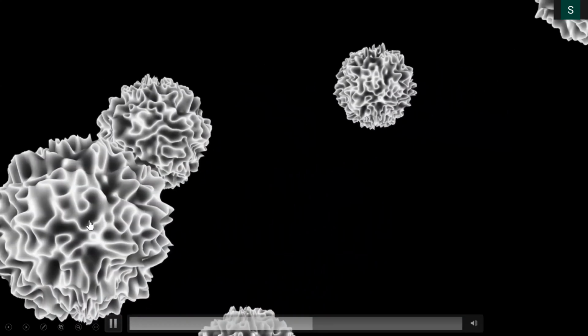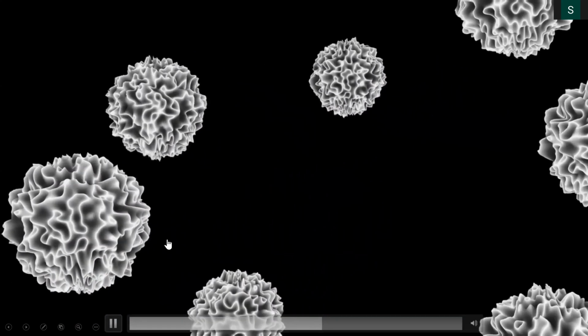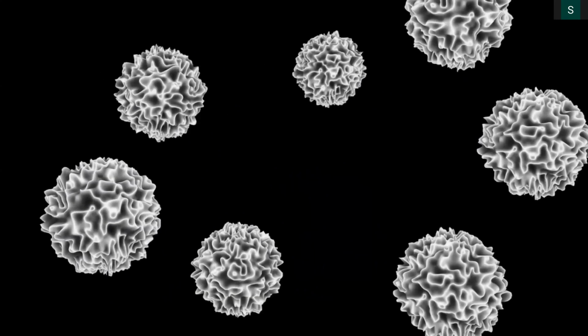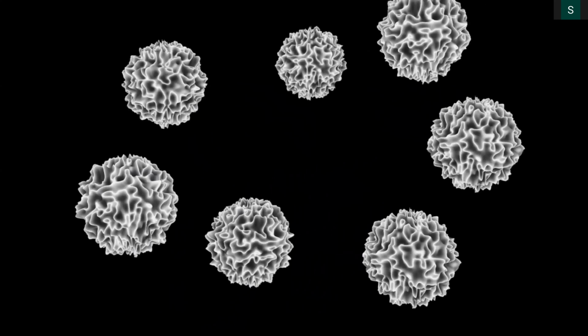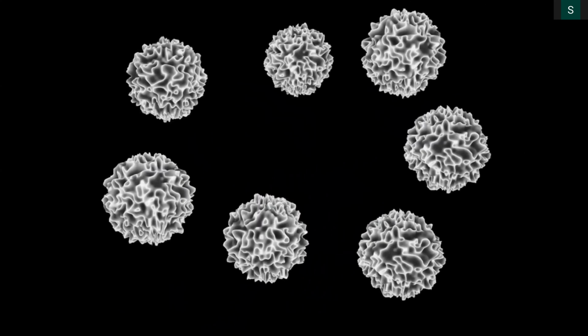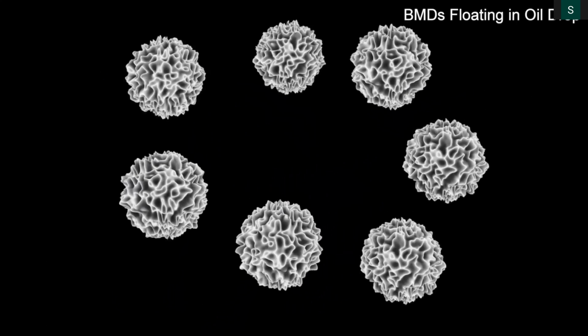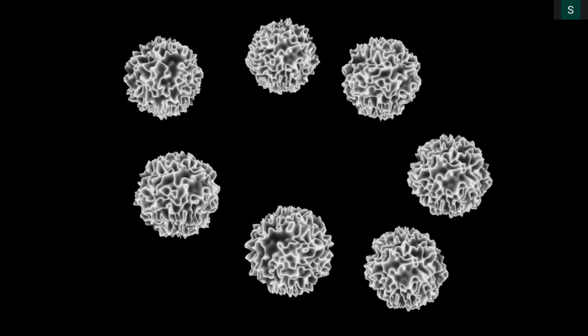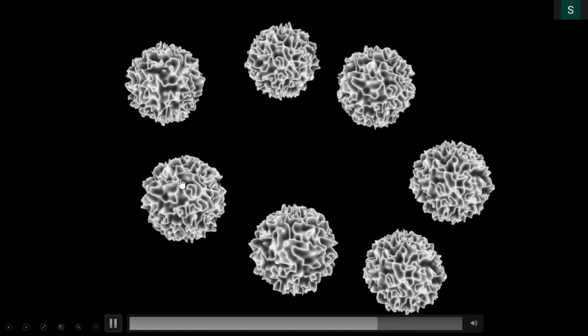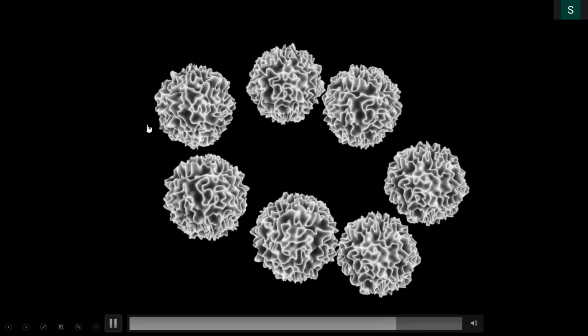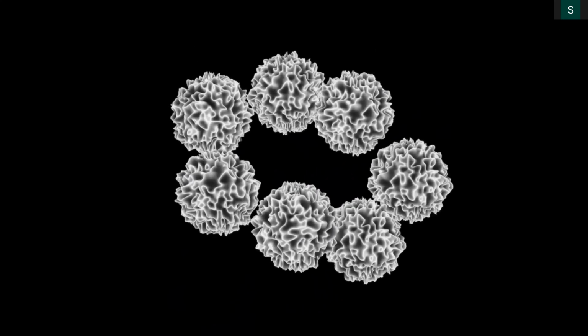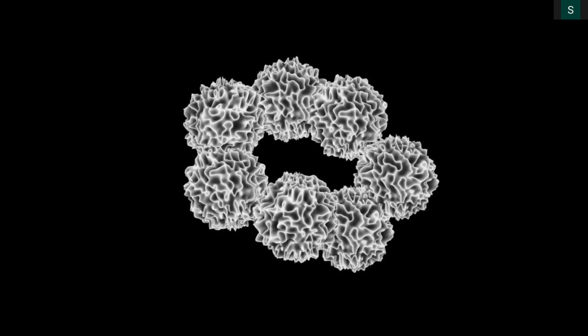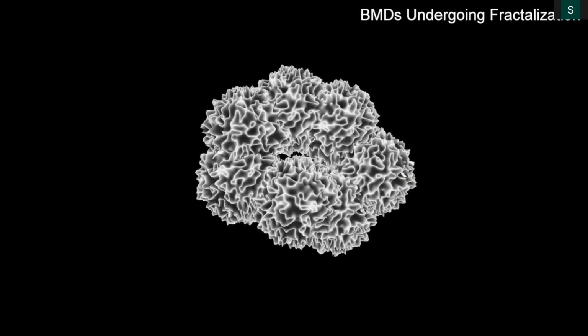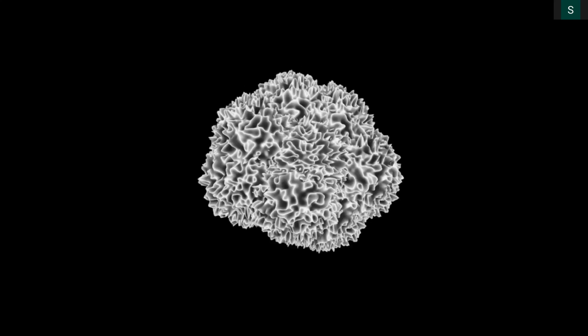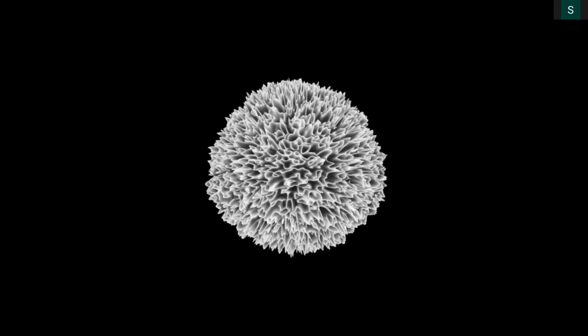Now you can grow your silica in these channels that you see. So by tuning the size of this droplet, I can tune the size of the DFNS. We can keep these droplets away from each other, you get a smaller particle, or I can merge them together and you get a bigger particle. We can also tune the thickness of each silica fibers, each silica sheets by changing the channel depth or channel width. So that's what we learned, that we can tune the sizes from 50 nanometer to 1200 nanometer at different ranges. We can also have one sphere with a different number of fibers.